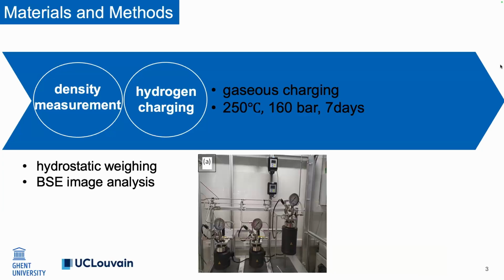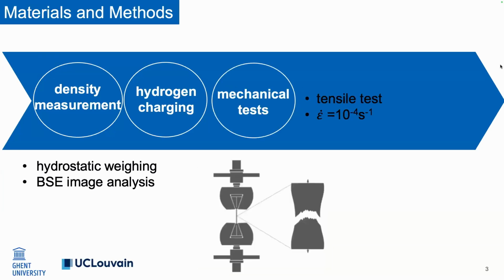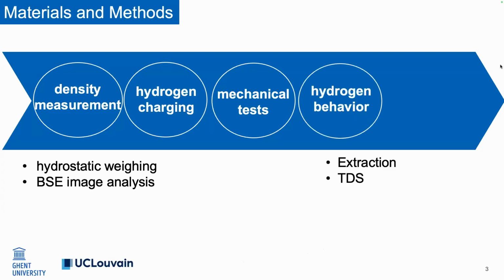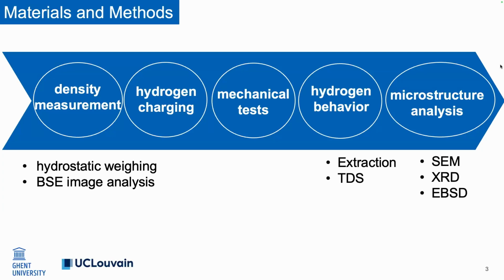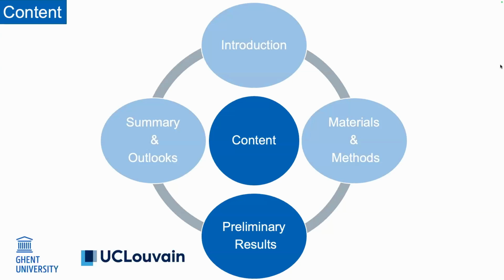And we charged these batches in an autoclave to introduce hydrogen inside the samples with the condition you can see, followed by some tensile mechanical tests. And we analyzed hydrogen behavior via extraction techniques and the TDS method. Also, microstructural evolution is analyzed via SEM, XRD, and EBSD.